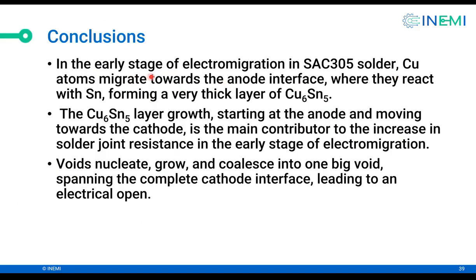So here's the conclusion. In the early stage of electromigration, before the resistance goes sky high, copper atoms migrate towards the anode interface. There they react with tin, forming a thick layer of Cu6Sn5. And this is what causes the increase in resistance. So as the Cu6Sn5 layer grows, starting at the anode and moving towards the cathode, that's the main contributor to the increase in solder joint resistance in the early stage of electromigration.